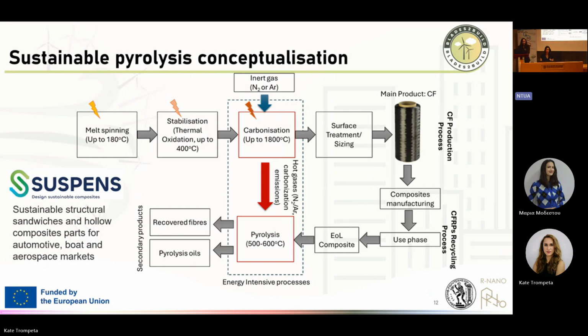The SUSPENS project deals with structural sandwiches and hollow composite parts from automotive, boat, and aerospace markets. And we have designed here in NTUA, in our laboratory, a new system that could combine the carbonization of carbon fibers production with the pyrolysis. So here we are trying actually to blend, to combine two energy intensive processes. The first one is the carbon fiber production that consists of different steps, as for example, the melt spinning, the stabilization, the carbonization, and the surface treatment.